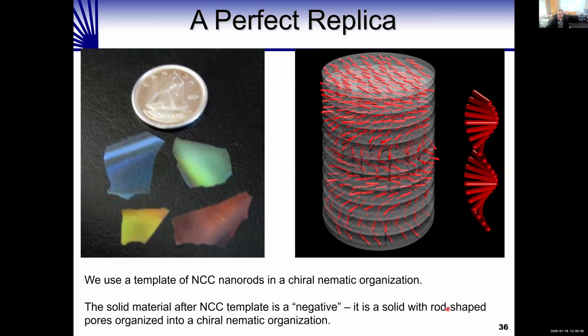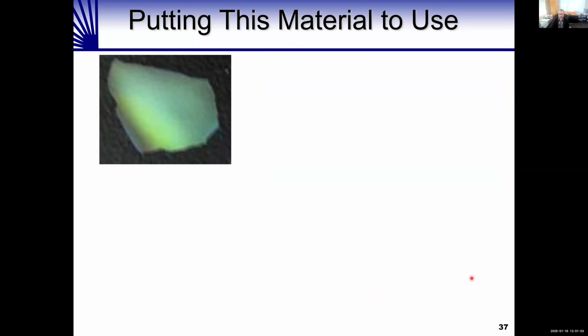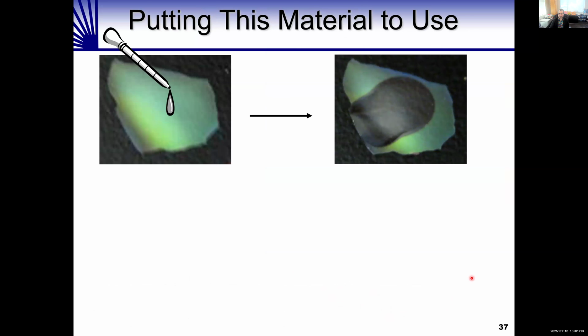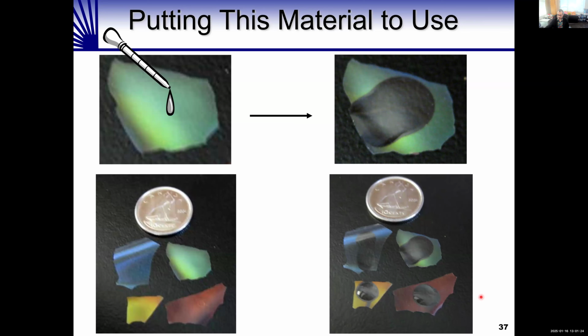So what can we do with this material? Well, one interesting thing is that it's very porous. If you take a film, in this case the green film, and add a drop of water to the surface, the water rapidly goes inside the channels and it becomes colorless and transparent anywhere the water has infiltrated, because the refractive index of water is close to that of glass. Here's a photograph of those four samples with droplets of water. If you dry them, it goes back to the original.